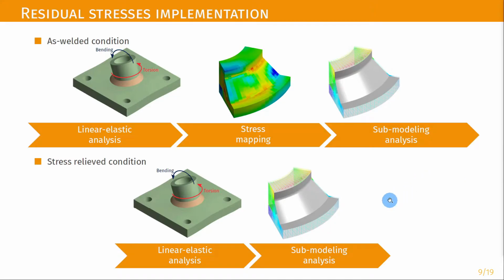From a numerical point of view, residual stresses were mapped and initialized within the submodel. Both as-welded and stress-relieved conditions have in common the linear elastic and submodeling analysis. The only difference here lies in skipping the residual stress initialization phase with respect to the stress-relieved specimen. It should be noted that radii of the weld root and weld toes have been included in the submodel. Radii have been derived directly from investigating cross-sections of the weld seam. As the derived radius of the weld root is 0.2 mm, its presence has a negligible effect on the initialization phase for the residual stresses, even if this is done directly within the submodel.